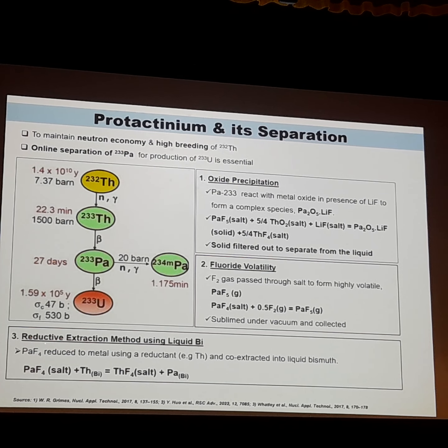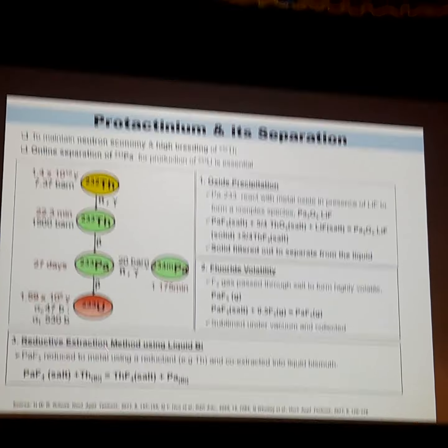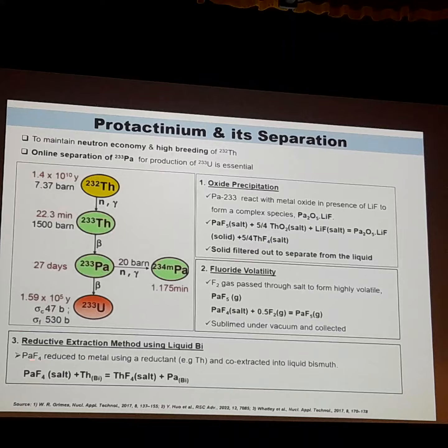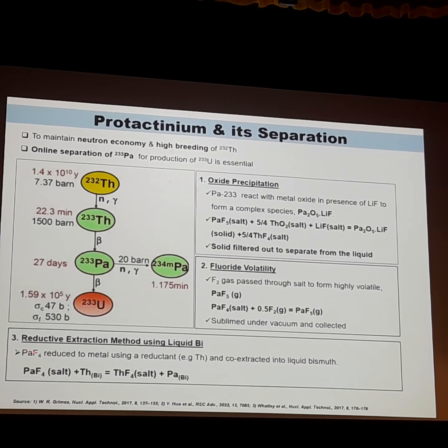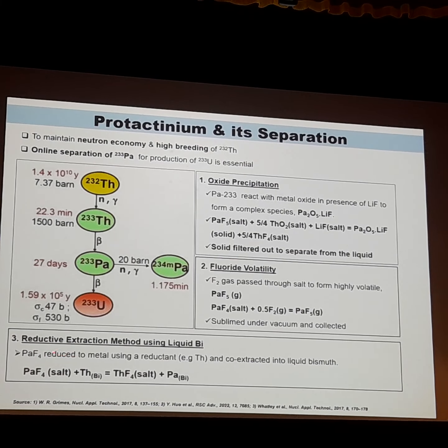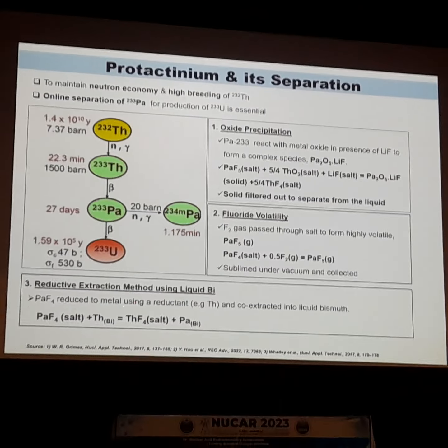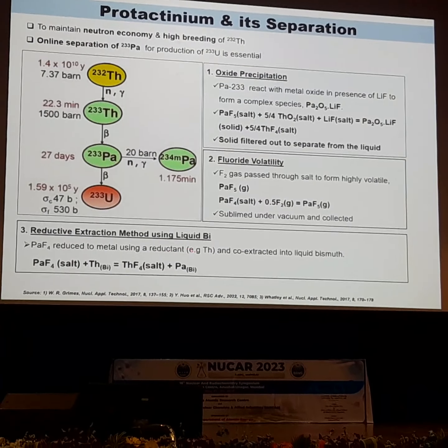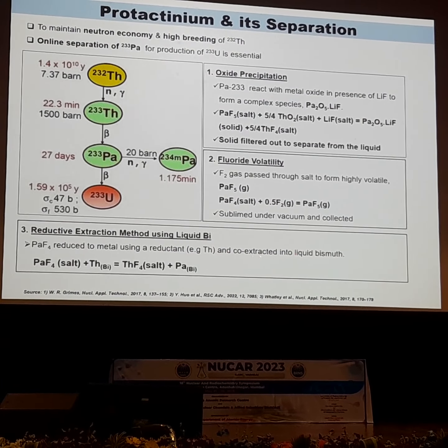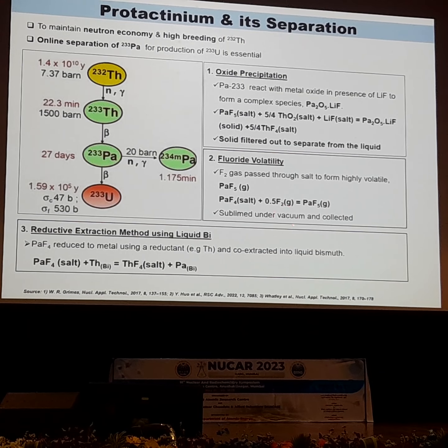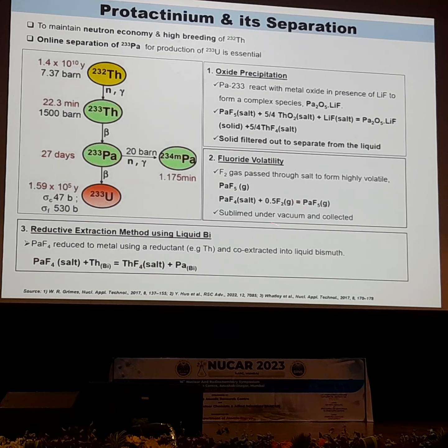Another, very well known, is the reductive extraction method using liquid bismuth. This protactinium tetrafluoride should be reduced with thorium metal as a reductant and then co-extracted with the liquid bismuth. Separation chemists are very well aware of these things.